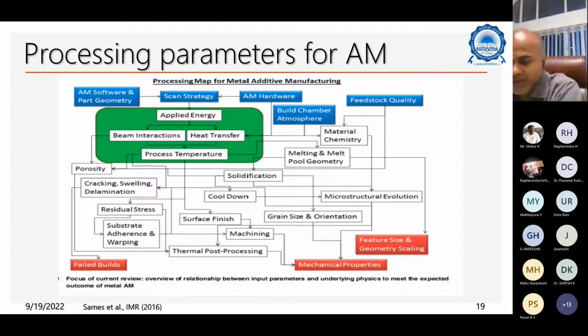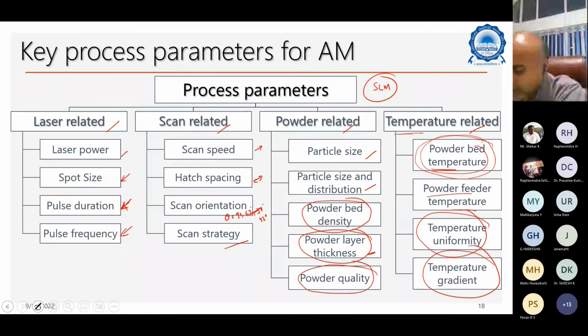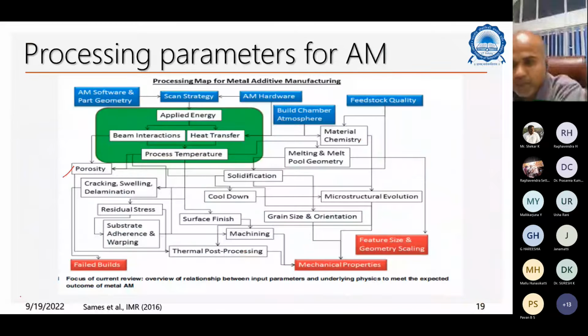These process parameters will affect certain end products. That could be the porosity. Whatever process parameters discussed before, if they're not optimally used in the processing of these components, you're going to end up with porosity, cracking, swelling, delamination. This mostly happens when there is a differential thermal gradient from one layer to another layer, and the residual stresses as well. Residual stress is another key problem in additively manufactured components,